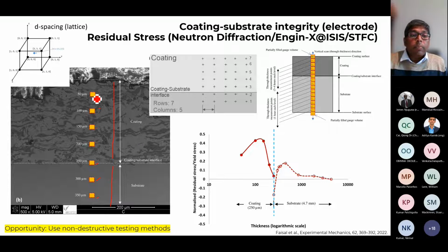Yes, and then each point measurement you do, neutron scanning. So each point takes about 4 hours. More time you spend at the interface, and then half an hour each in the substrate. So what happens, you actually measure the d-spacing in the lattice and use a formula to find the strain build-up through thickness. Assume you have a very high tensile stress in the surface region and very high compressive.